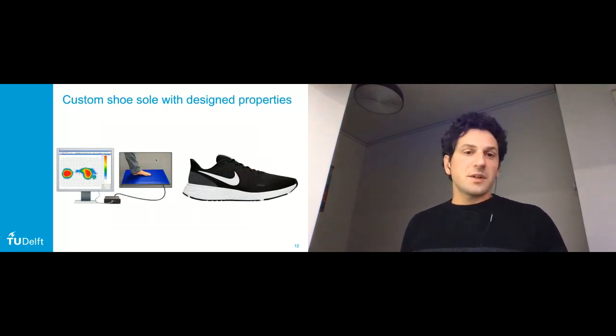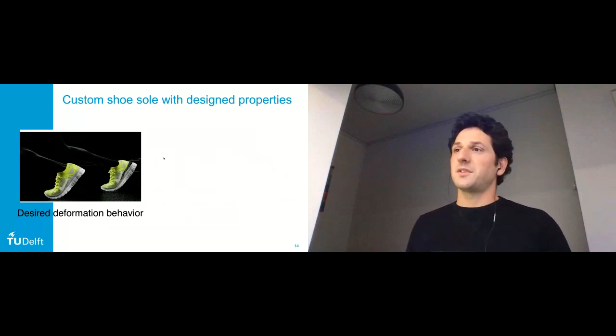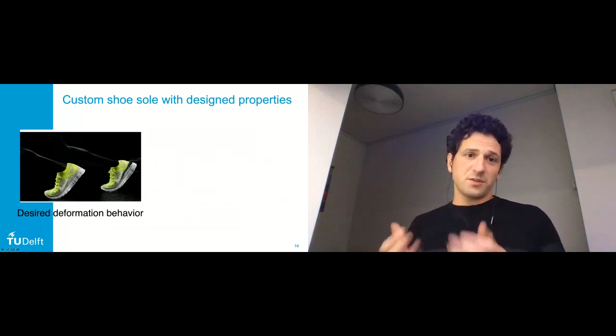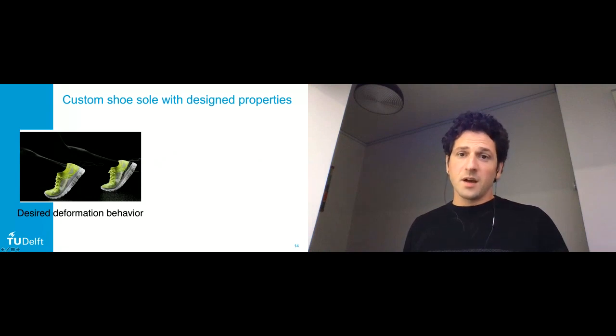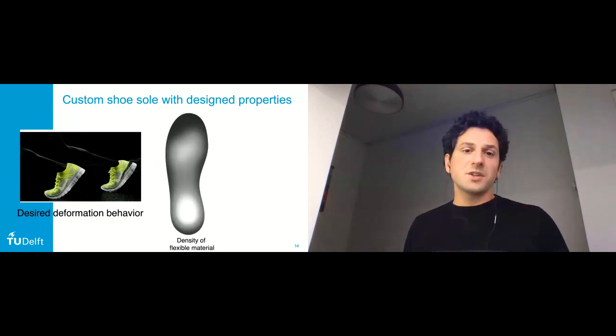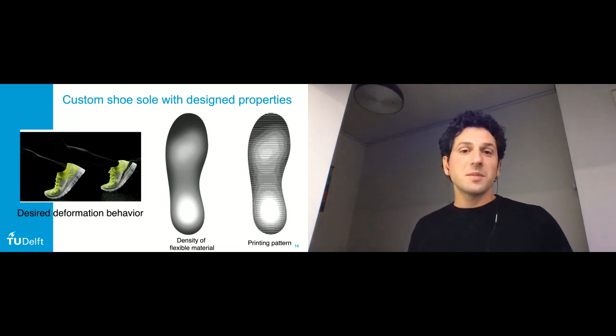For example, going back to the example of the custom shoe sole, say that apart from this desired distribution of flexible and rigid to avoid, for example, pressure points, we also have a desired deformation behavior. Say we want the sole to be able to bend in this mode, but to be stiff in other modes. Well, one possible way of still achieving this density distribution of flexible material, while still obtaining this desired deformation, would be, for example, to create a printing pattern that looks something like this, with horizontal lines again running through, which would limit the deformation behavior to the deformation behavior that we defined at the beginning.